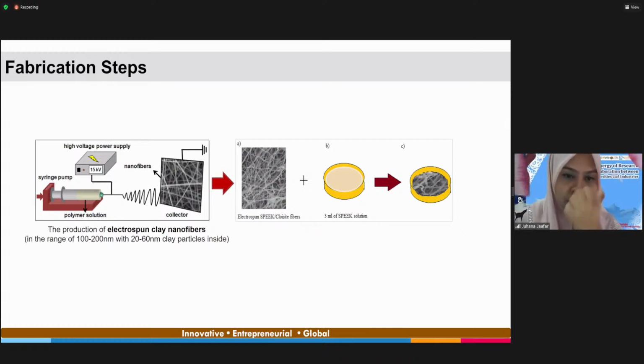And this is the fabrication step that we use to produce the clay nanofiber coated SPEEK membrane. What I mean by coated SPEEK membrane is that the SPEEK membrane is the polymer base that we use in the membrane. So we coat with the nanofiber, but during making the nanofiber, we use the formulation of SPEEK as the polymer carrier, together with the clay as the inorganic material. So in fact, the nanofiber consists of SPEEK and also clay. And again we have the SPEEK solution as the base polymer, so we will incorporate the electrospun clay in the SPEEK polymer carrier into the SPEEK solution here.